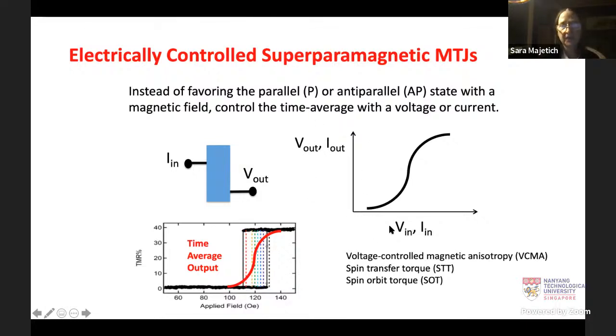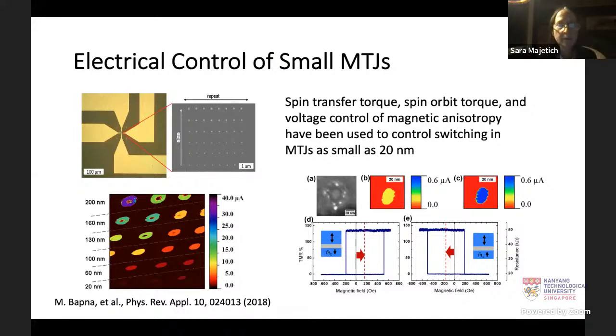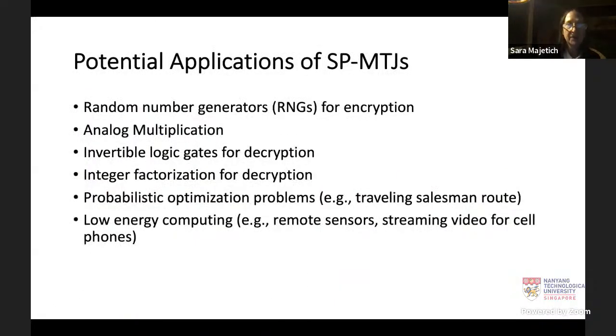So fortunately, with magnetism, we've got lots of options. We've got voltage-controlled magnetic anisotropy, spin transfer torque, and spin orbit torque that we have worked at. And so I'll tell you a little bit about those, though we won't do a lot with spin orbit torque. We have done it for switching for MRAM kind of devices, so it certainly is feasible. It's just more wiring involved, so it's a little bit more complicated. But what we were able to see is this effect can be used to switch or to characterize devices as small as 20 nanometers. So you really can get down to small sizes. The question is, what kind of design and what kind of electrical control is going to be best for particular applications? So of the potential applications, random number generators are a big one.